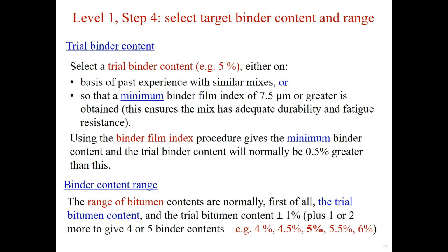Normally, the binder film index gives the minimum binder content, and the trial binder content will normally be 0.5% higher than this. By using the trial bitumen content, plus and minus 0.5% and 1%, we're able to get a range of bitumen contents.